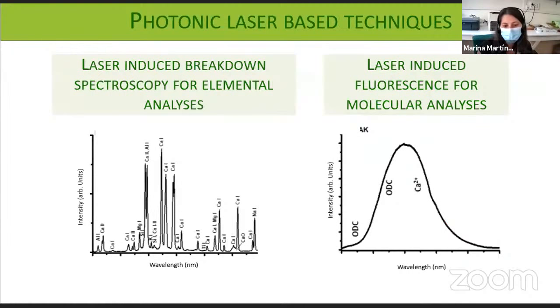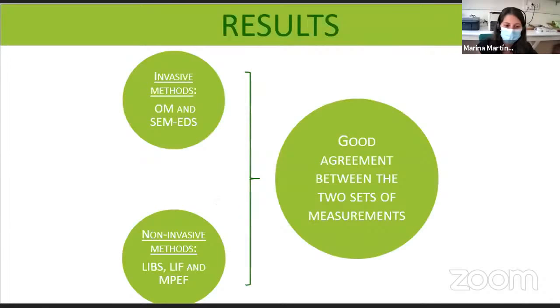Also, we use laser-induced breakdown spectroscopy and laser-induced fluorescence techniques to determine the elemental and molecular composition of the glass. Moving to the results, firstly, in relation to the composition of the glass, apart from providing complete chemical information at molecular level, the obvious benefit of applied laser spectroscopy is its non-destructive character, as well as its capacity for in situ analysis. Secondly, as we already said, concordance is shown when comparing the thickness of various glass alteration layers as determined by multiphoton excitation fluorescence and optical microscope in cross-section modality.